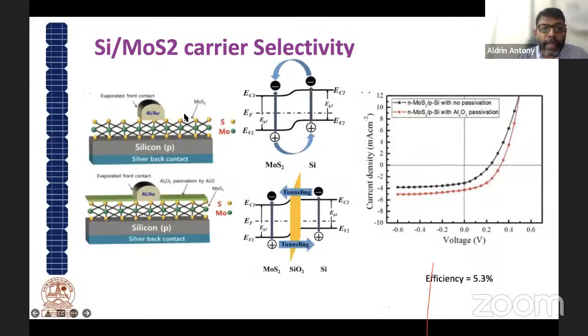Another one I'm showing is a silicon MoS2 carrier selectivity. If you put MoS2 over the silicon, it forms the bands bending in this direction. This molybdenum sulfide forms a Schottky junction with the silicon, the band bends down, and the electrons can move in this direction, and also the holes can move in this direction. MoS2 on silicon forms a very good band bending, and the holes from here cannot move in this direction because of the band offset. So electrons move in this direction, holes move in this direction. An efficiency of 5.3% has been demonstrated using 2D materials as a carrier selective material in solar cells. So this is a futuristic application of solar cells.